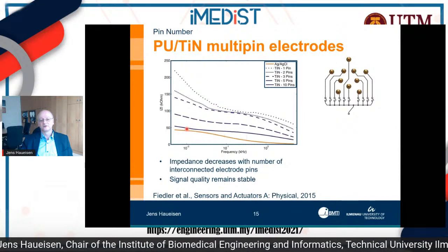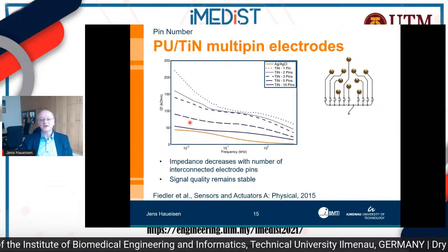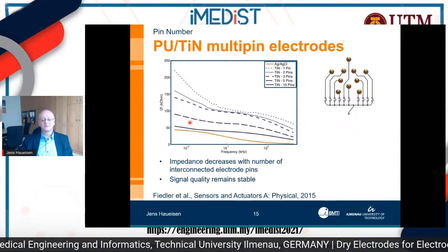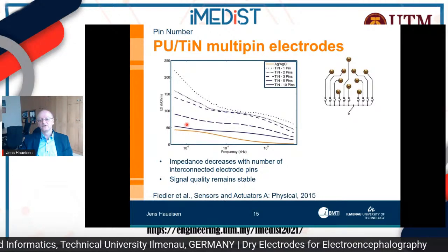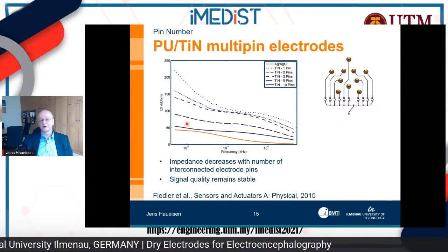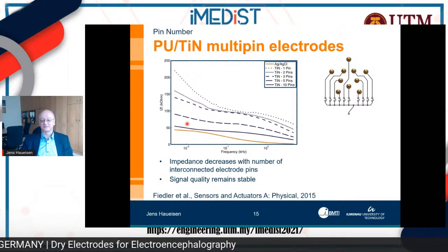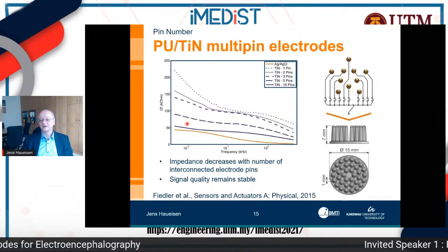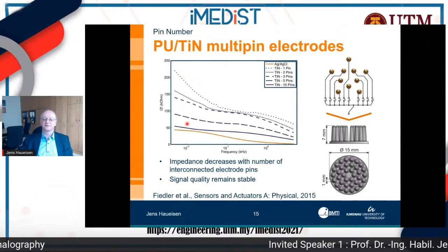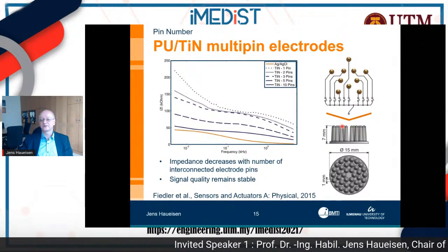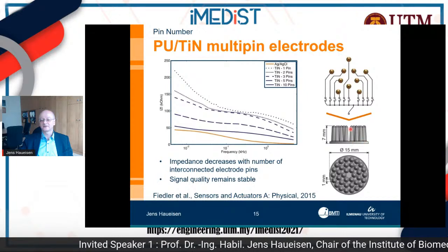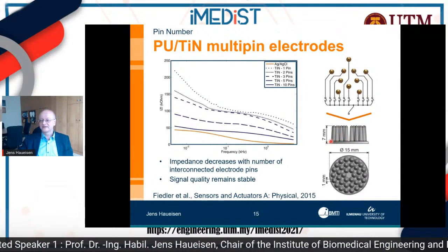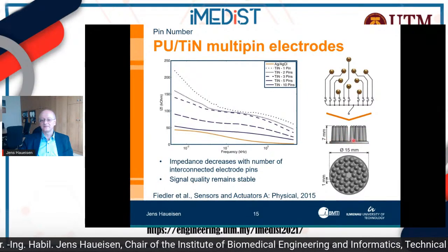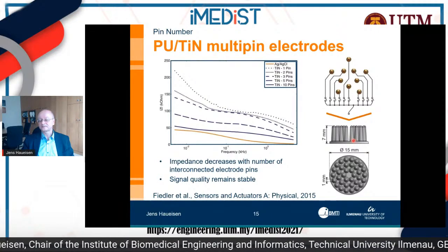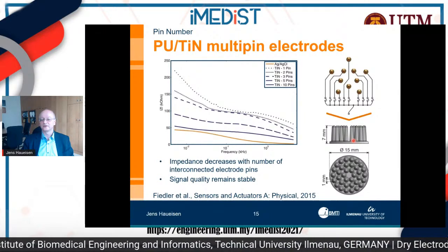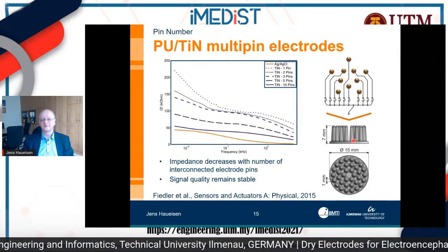So in other words, we concluded from this experiment here that roughly about 10 pins, maybe a bit more than 10 pins, are sufficient for our typical recording setups with this type of pin electrode. And this led us actually to the design, which you see here, where you have pins integrated on one base plate, so they're connected all together, such that you have basically one and the same base plate for one electrode and not one pin.